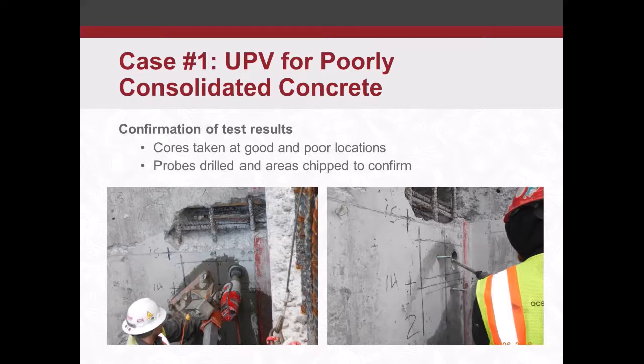In the core that we took at the bottom, in that photo there on the left, we noted that there was an anomaly at that location. We cored that location, and we found some ping pong ball, golf ball size voids in the core. So we kind of validated some of our data there. And depending on the purpose of the project and the purpose of the testing, it's sometimes good to do some destructive testing to confirm some of your results. Sometimes it's not necessary, and we can see some of those situations a little bit later on.